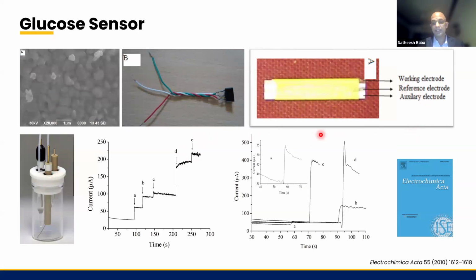And this example is a kind of frugal innovation where we developed a catalytic material that specifically oxidizes glucose, and we just coated it on a small plastic strip, which is very similar in size to the commercial glucose sensor strip. And this is actually a very handmade one. Then I tried integrating that using a small IC pin. I just removed the inner plastic. Then I was able to connect that with the electrochemical station and test with various concentrations of the sample. Then I was also able to test with real samples. These three, C, D, and E, represent a hypoglycemic patient sample, a hyperglycemic patient sample, and a normoglycemic patient sample. So we were able to get quantitative results with this.